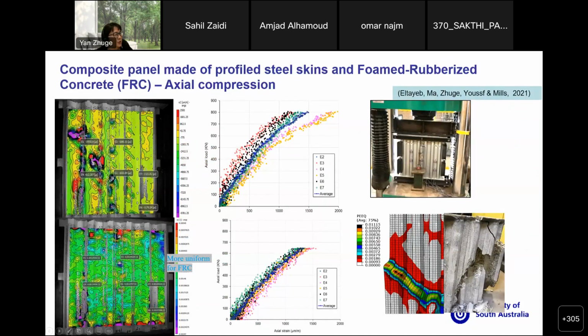Here I show you some testing results for the actual compression test. You see the test setup for the composite walls. We're using digital image correlation, DIC, to measure the strain and deformation of the whole surface of the steel sheet, and also using a 3D software package to measure all the deformation changes. You can see from these two diagrams that the steel strain distribution is more uniform in the wall with foamed-rubberized concrete compared with the one with normal concrete. It also has less cracking and more ductile performance.